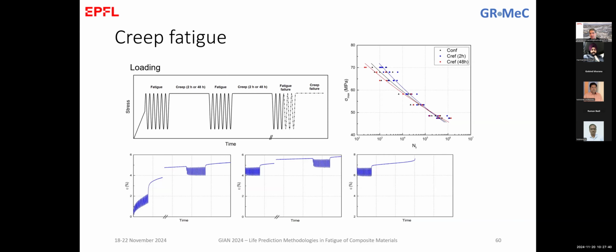48 hours. And it is very interesting to compare these curves and see exactly the effect of creep at high stress levels and low stress levels. If I focus on the high stress levels, here we see that creep for a few hours, 2 hours, so the blue line, is beneficial. It gives better fatigue performance than the normal specimens that are continuously loaded up to failure. When we let creep for more, it gives the opposite effect. The curve turns to the left, and this is exactly related to what we discussed before.